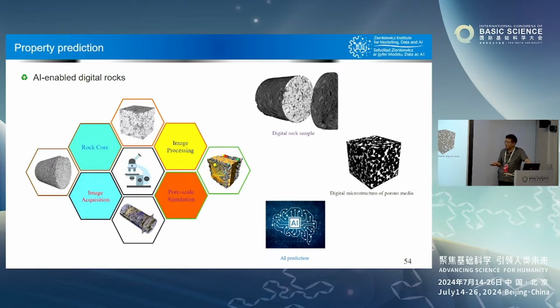Is it possible to use an AI model here, so that you don't have to do all that up to here, and then you get your result? It is possible. What that would need is a data set to train. Your data set would have many samples, and for each of them, you run your simulation for permeability, so you have that pair labeled. For each of these, permeability is predicted from your physics-based simulation. A lot of pre-computation. We tried that.